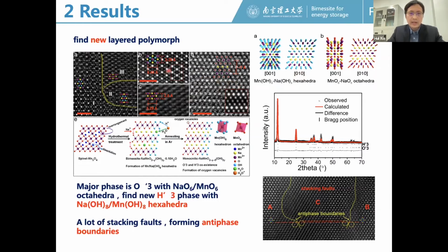So based on these atomic arrangements from different directions, we construct the structure model for this new phase, which we call the H3 phase, because this new phase is composed of this manganese-oxygen-hydrogen hexahedron, but not the normal manganese-oxygen octahedron. So which means we actually find a new layered polymorph in this Birnessite structure, and we think this new phase is the key that can stabilize this layered structure when we remove all the crystal water, and it can retain a large interlayer distance.